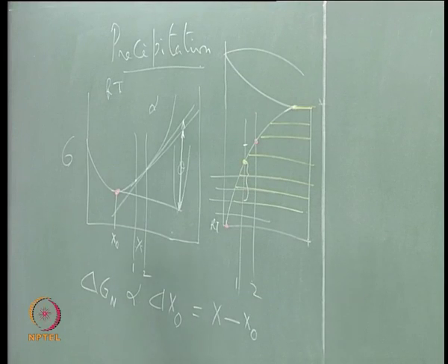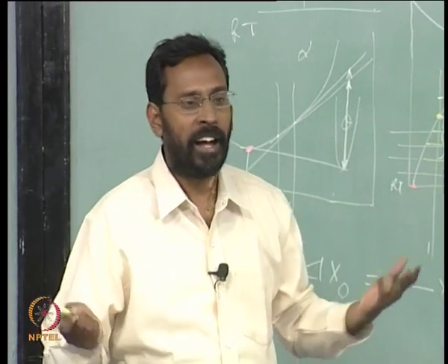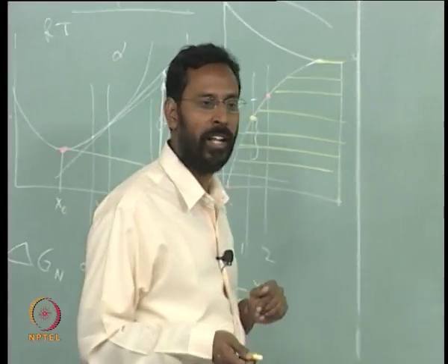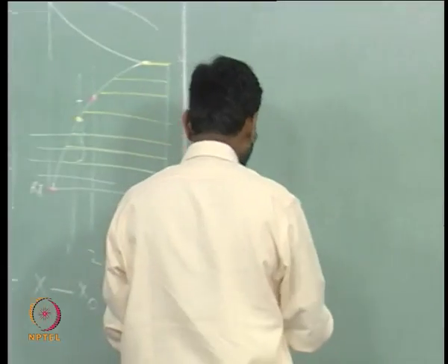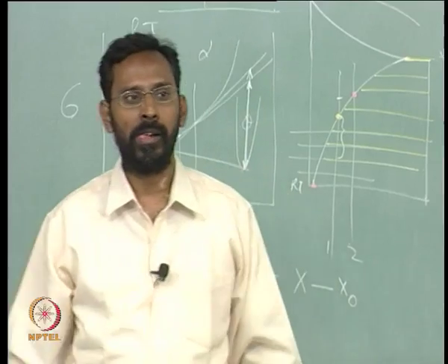Theta is still at the grain boundaries. Though it has dissolved, some amount of theta is still left at the grain boundaries, because solidification happens under slow conditions. As a result theta precipitates at the grain boundaries only. So you will see that the theta is there at the grain boundaries, but the matrix got enriched, but still you have theta here. And so, if from that temperature I quench it, what should happen?